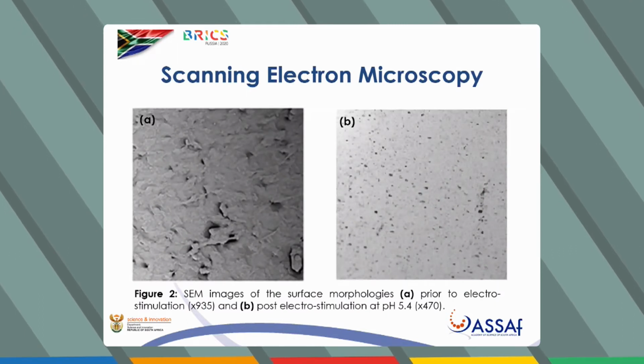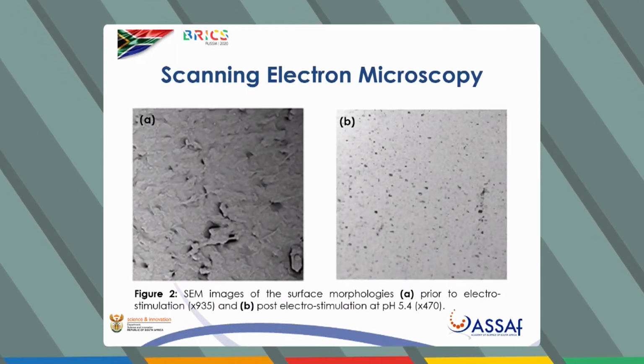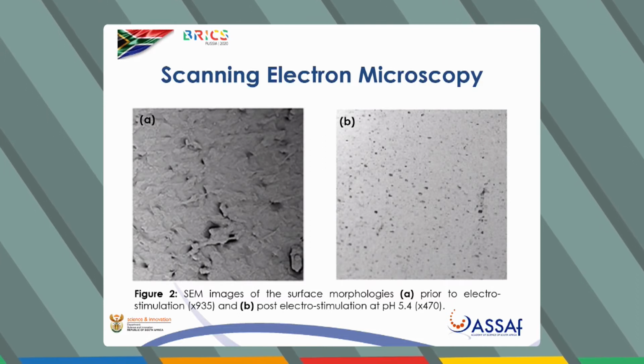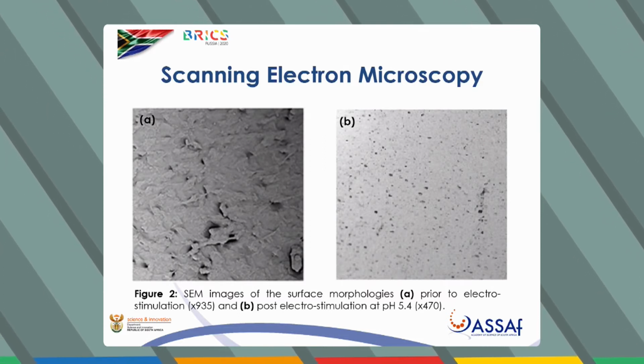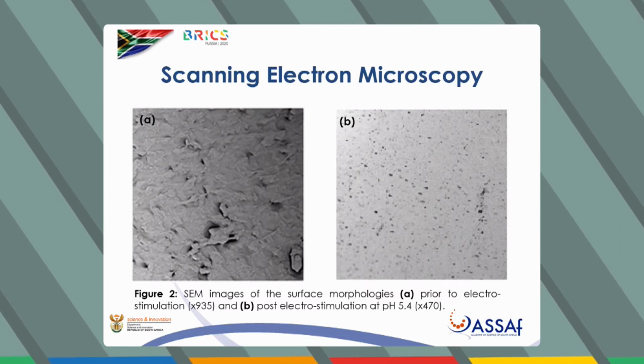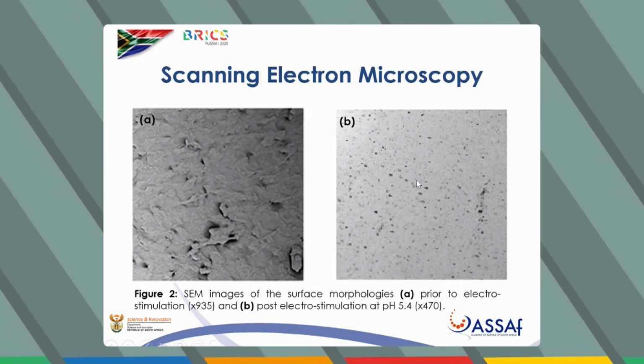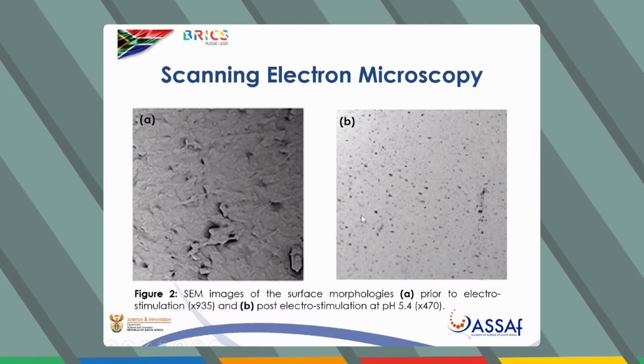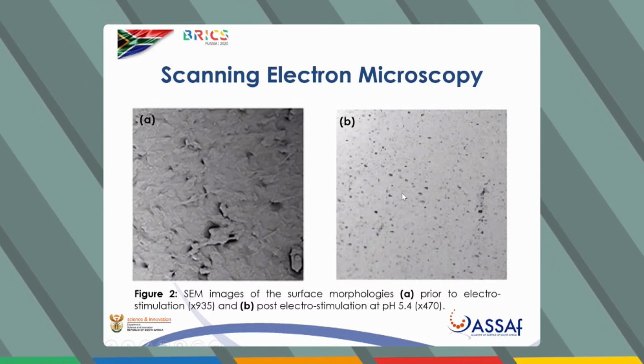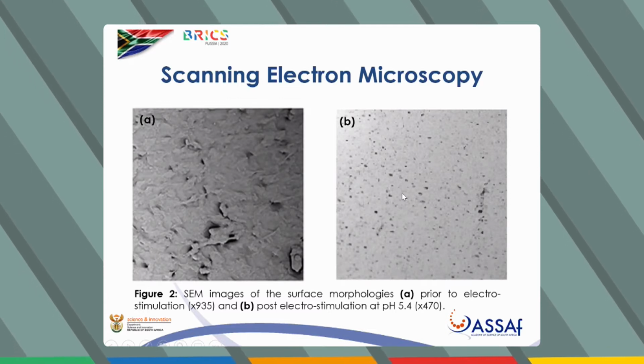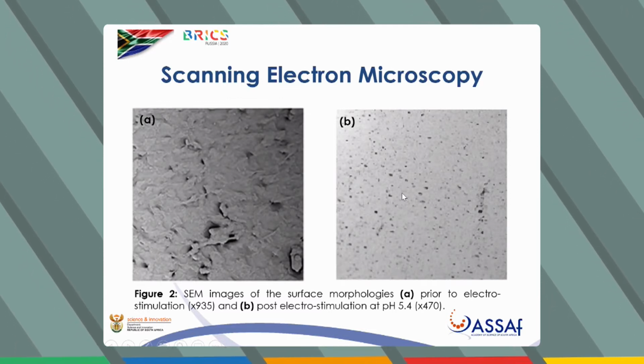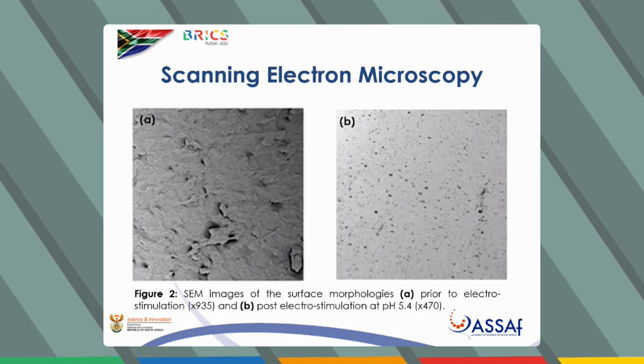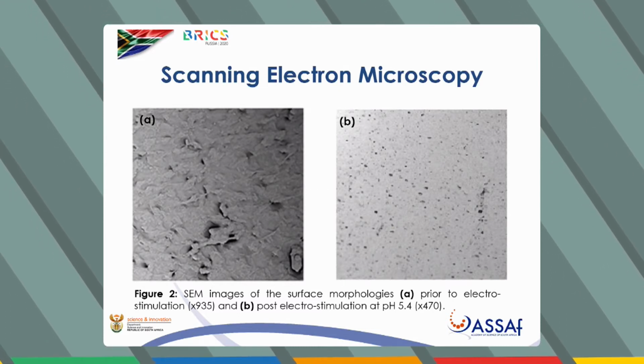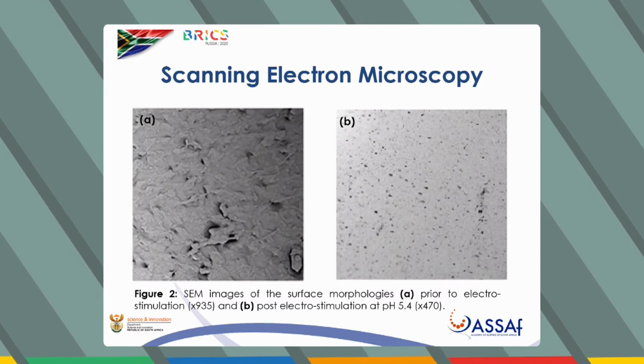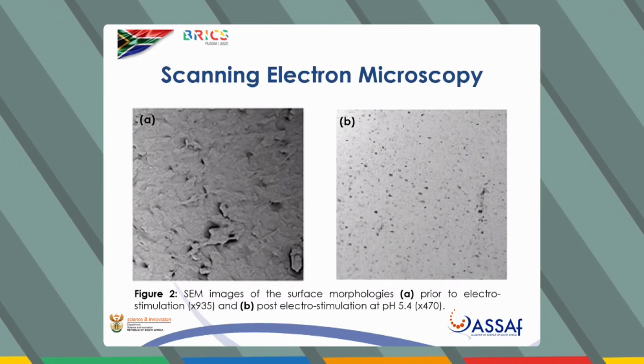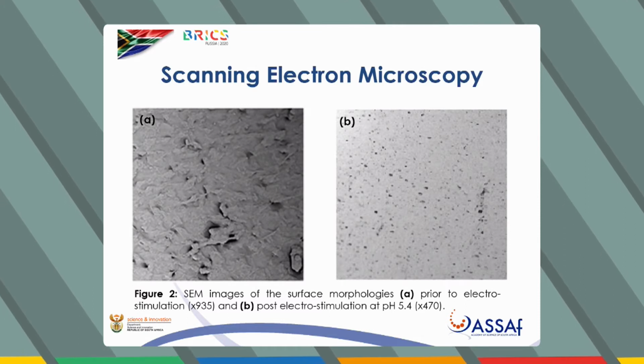From scanning electron microscopy, it showed that when the BiPERG was exposed to simulated transdermal conditions, as well as electrostimulation, there were changes in the surface morphology of the BiPERG. As you can see, there are pores present in the surface of the BiPERG only after electrostimulation. Since in the study the electrostimulation was the only change in the environment, it can be concluded that the pores were formed as a result of the polymeric network opening in response to the applied current. So that was one of the ways where we proved the electroresponsive capability of the BiPERG.